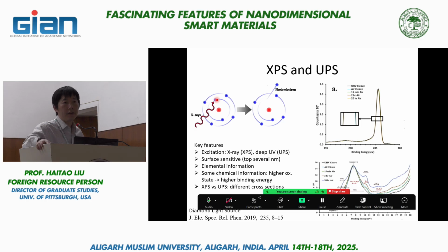The mean free path of a lot of photoelectrons in solid state material within the context of XPS is a couple of nanometers, maybe tens of nanometers in some cases if you're lucky. So in other words, only the top few nanometers of material can generate photoelectrons that can escape. Additionally, because the mean free path of the electron is so short, the most likely survival pathway of the photoelectron of getting out of the solid material is going vertically up.